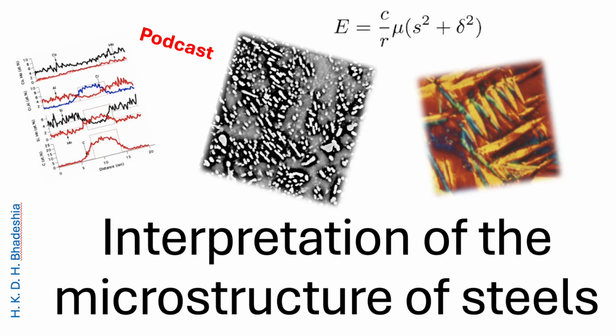Speaking of shaping the structure, what about spheroidization? If pearlite is inherently layered, why does heating it cause those layers to ball up? It's pure thermodynamics. Spheroidization is just driven by minimizing interfacial energy. Right, a sphere has the minimum surface area for a given volume. Exactly. So the heat treatment lets the cementite lamellae break up and spheroidize, and it greatly reduces the total ferrite-cementite interfacial area. It happens much more easily in fine pearlite.